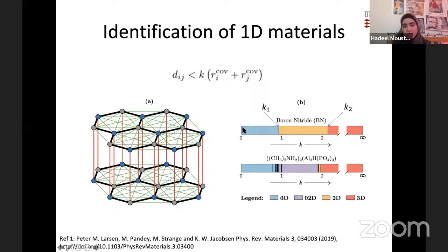So at a low value of K, no bond exists between the atoms, and then we are only dealing with the atoms themselves, and then it's a 0-dimensional material. And then when K increases, the bonds begin to set up between the atoms, and at a certain value of K, K1, we have a 1D component that appears, and then when K increases to K2, the 1D component disappears, and then we have a 2D or a 3D component.